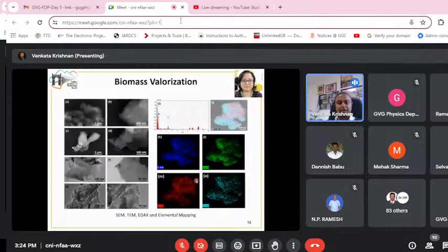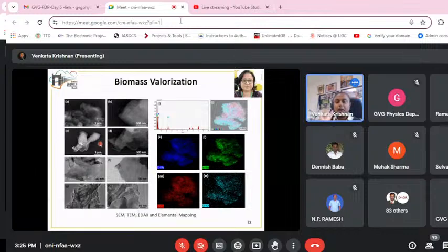Another property is the physical feature or shape of the material. For that, we used scanning electron microscopy (SEM) to get an idea of the physical feature or morphology of the material, and further morphology was obtained using TEM. SEM indicates the morphology of the sample at the micrometer level, whereas TEM indicates the morphology of the sample at the nanometer level.